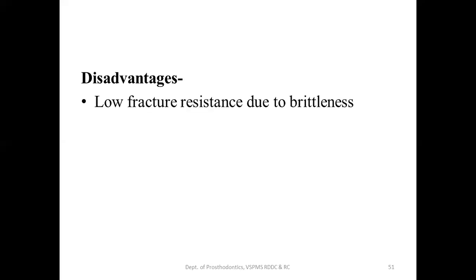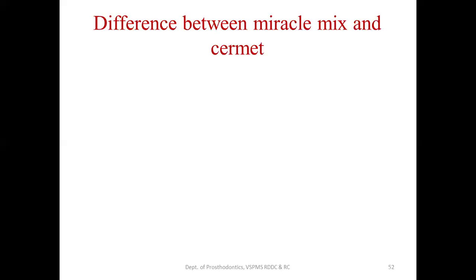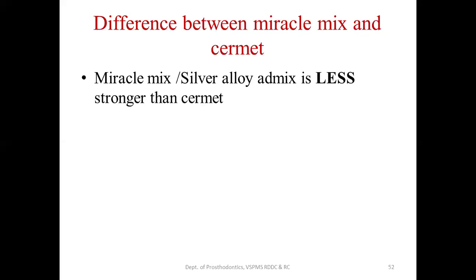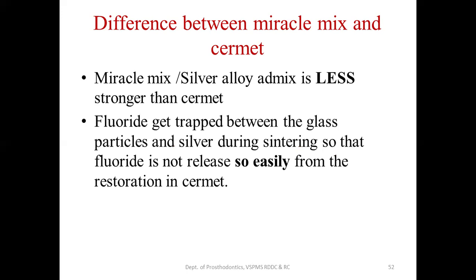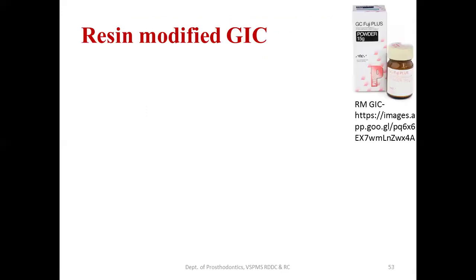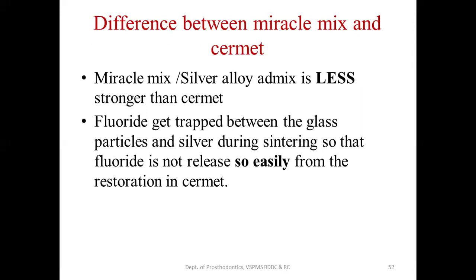Now, the disadvantages are low fracture resistance due to brittleness, more opacity, and poor aesthetics because silver is added here. So, what is the biggest difference between the miracle mix and the cermet? The miracle mix, the silver alloy admix, is weaker than cermet because it is not made by the sintering process. The fluoride gets trapped between the glass particles and silver during the sintering, so fluoride does not release easily from the restoration in the cermet. That's why you will get a less anti-cariogenic property in the cermet as compared to the miracle mix. These are the two differences between the miracle mix and the cermet that you should remember if somebody asks you.